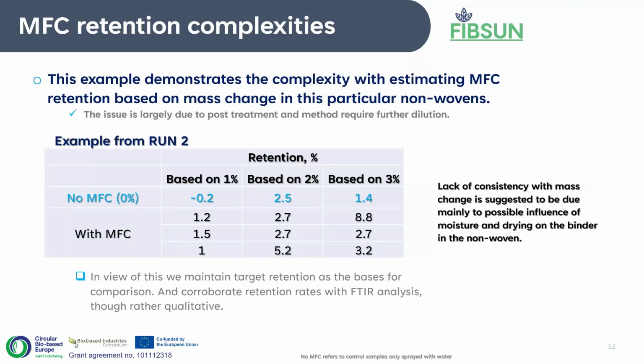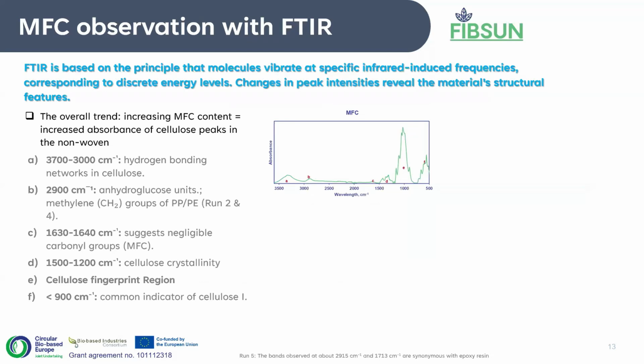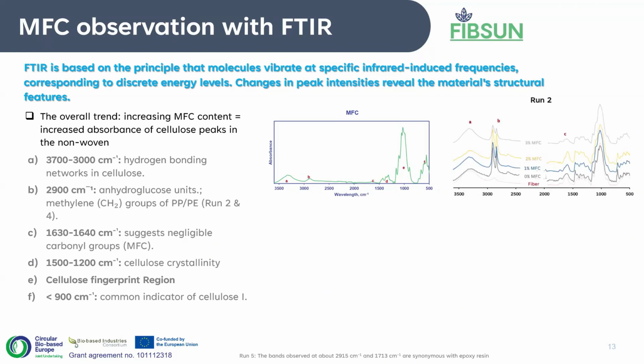So to check, because in our case, we could say for sure we see visibly that after spraying there is MFC on the non-wovens, but scientifically we needed to also be able to prove that, and we corroborate this with FTIR analysis, first by understanding the structural properties of the MFC. For this we see the common typical bands which are typical for cellulose material. But in any case, we see some differences when you think about lignocellulosic material. For instance, we have included fiber FTIR here, and we can see a clear difference between fiber FTIR and MFC at the 1650 range.